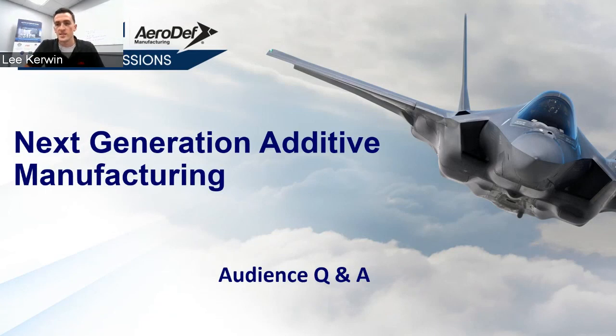So we didn't deal with materials outside of laser powder bed fusion that needed an inert atmosphere. The aluminum that was deposited on top of the part to encapsulate the sensor, the Fabrisonics process is a solid state process, so that aluminum can be deposited in the atmosphere, and it doesn't have to be in an inert environment, because you're depositing it in thin strips using ultrasonics. I can see there would be some potential issues depending on what type of hybrid you're doing and what the material is, that you could need an inert atmosphere. But that's kind of why we went the direction that we did, so we wouldn't have to take that into account for the second and third processes that we were putting into that part. Hope that answers your question, Robin.